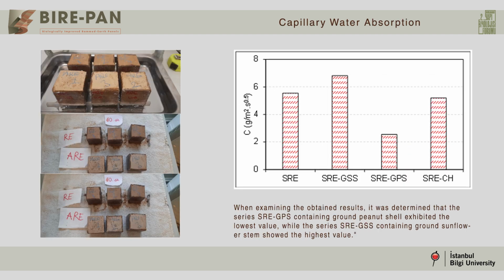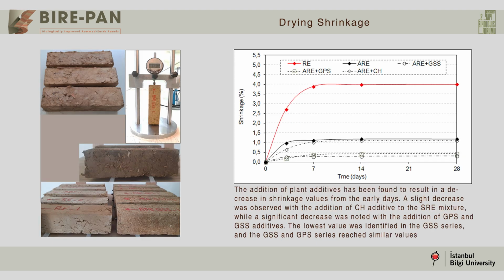When testing the capillary water absorption, it was determined that the series containing ground peanut shell, GPS, exhibited the lowest value, and the series with ground sunflower stem, GSS, showed the highest value. And additionally, we added plant additives. Drying shrinkage: a slight decrease was observed with the addition of corn husk additive to the mixture, while a significant decrease was noted in this series. GSS series and GPS series reach similar values.